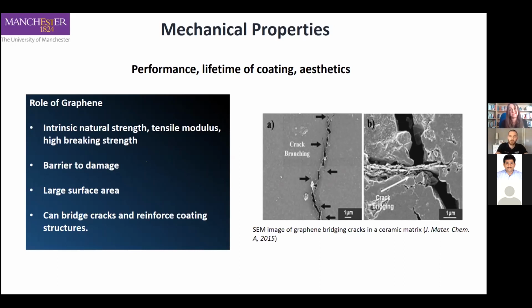It's got really high tensile strength and modulus, and this strength is down to these strong bonds and the way it's covalently bonded together. When it's subjected to mechanical force, graphene can also transfer stress very effectively because of its structure through a matrix material, and it can help to stop crack propagation or even bridge cracks. And again, that's down to its unique structure.